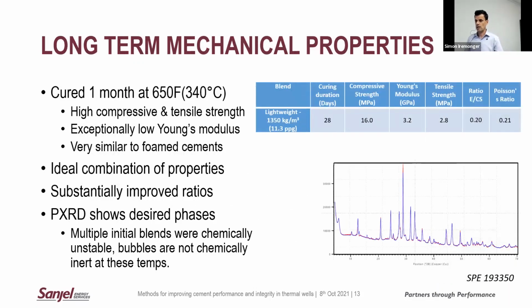And kind of just giving a high level summary of some of the properties that we observed when we made this lightweight cement, and this was a system down to about 1350 kilograms per cubic meter, or just over 11 pounds per gallon. And these are mechanical properties after 1 month at 340 degrees Celsius, 650 F. So still maintaining an excellent compressive strength, very nice low Young's modulus of 3.2, a high relative tensile strength, certainly substantially above that 10% of compressive that you typically would expect to see, and a nice low ratio of your Young's modulus to compressive strength. And these properties are pretty comparable to that of a foam cement. So really a nice ideal combination of properties there. And of course, whenever we're looking at this, we're always looking at the X-ray diffraction analysis as well, making sure we've got the desired phases, which in this case is xonotlite.